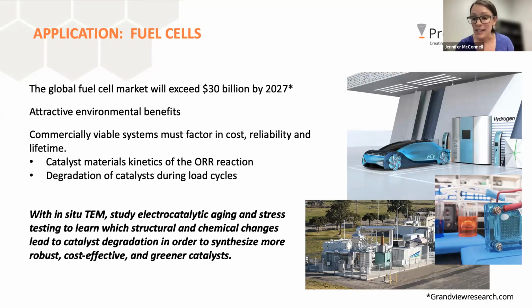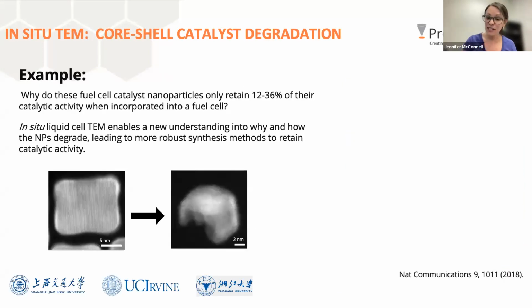With in situ TEM, you can actually watch these catalyst particles and see the electrocatalytic aging process. You see the surface-to-volume ratio decrease as the particle grows, the pathways by which that happens, and the conditions under which it happens. You stress test to learn the structural and chemical changes that lead to catalyst degradation over time. Again, you see it. Once you know what not to do, it helps you investigate what might be good to do. So this works really well for catalyst studies in addition to batteries.